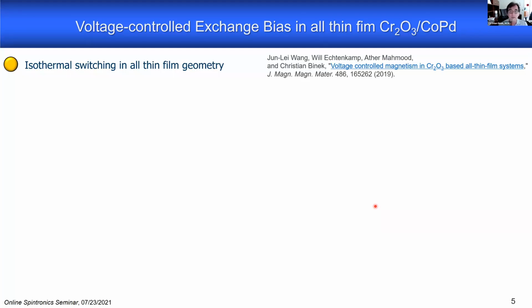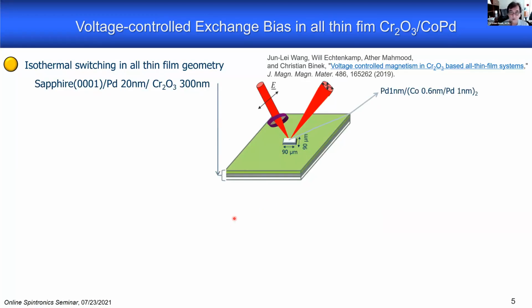Many groups started to work on this. I show you our results, which took us a long time to get there, and it also reveals some problems, which I want to point out in a minute. So here you see a chromium oxide thin film. It's not particularly thin. It's still 300 nanometers thick, but it's certainly no longer a bulk single crystal. And on top, we deposited a small cobalt palladium structured square. Why a small one? Well, that was already an insight, because if you make it larger, then of course you pick up all the potential defects that give rise to leakage. So in this sense, scaling here is your friend. If you make things smaller, you can combat leakage issues that appear in thin films to some extent.